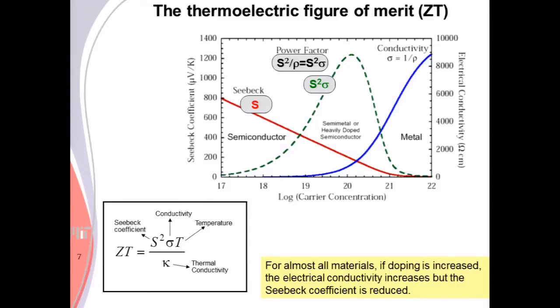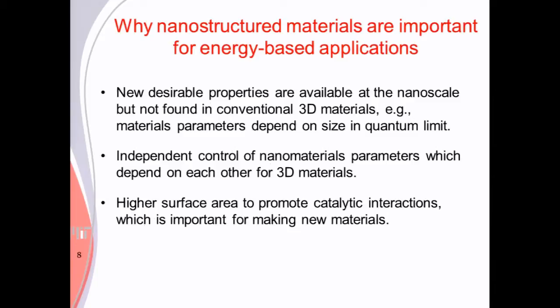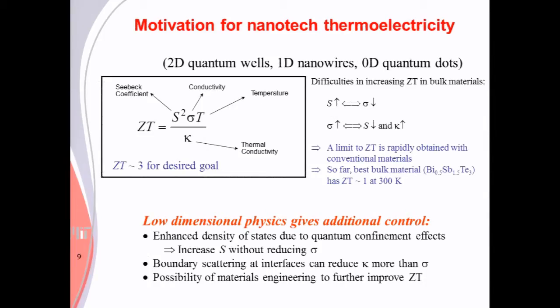So this again shows, I'm sure you've seen this many times, that when you have a high Seebeck coefficient, which you must have to have good thermoelectricity, then the electrical conductivity is very poor. And somehow you have to have this product, S squared sigma, large, and the green curve shows that there's a compromise between these two. There's also a contradiction in the conductivity: when sigma is large, then kappa will be large because the electrons will carry heat as well as electricity. So we have a problem on our hands, and this has been perplexing us for the last 20 years, but we made progress. And we continue to make progress.